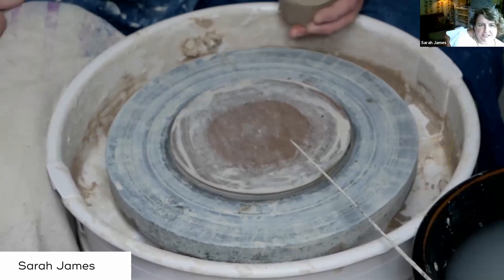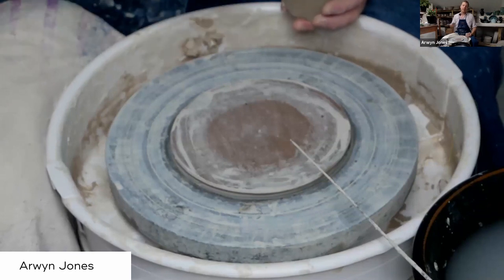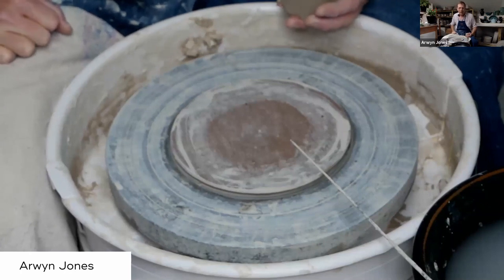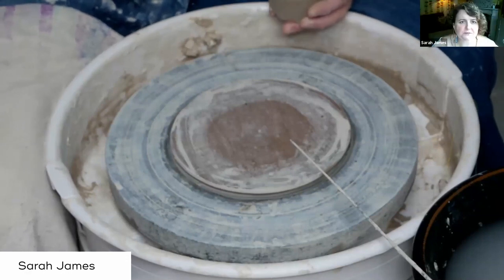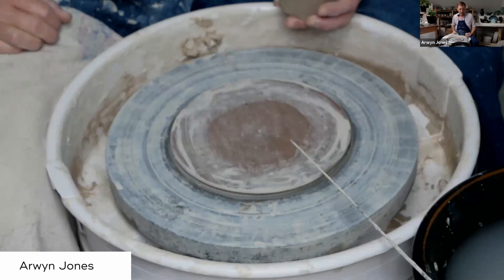It's a stoneware essentially, is it? It is, yeah. I fire to cone 9 in my electric kiln, which is the oxidized work, and I've just started doing some reduction work, which is cone 10, a little bit hotter. So from 1260 to 1285-ish. The greens are fine, and my pale blue, the work that most people know me for, is all fired in an electric kiln. So it's oxidized, and that's the work I've been making basically since I left college.